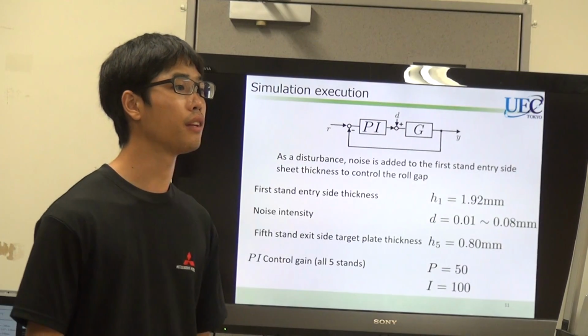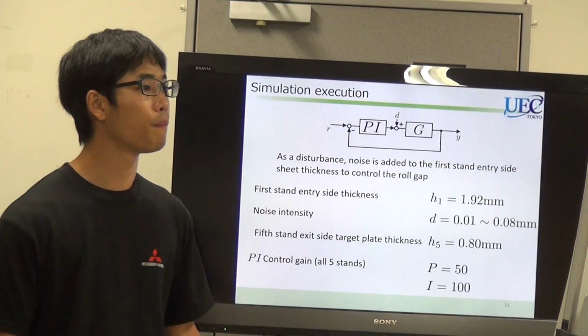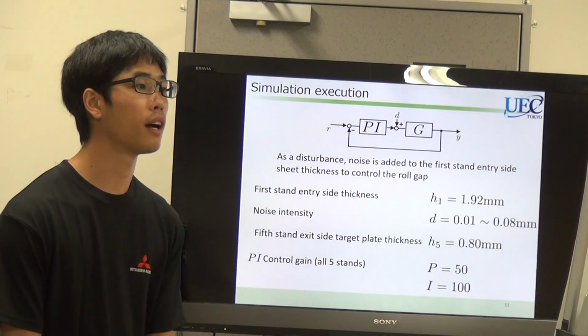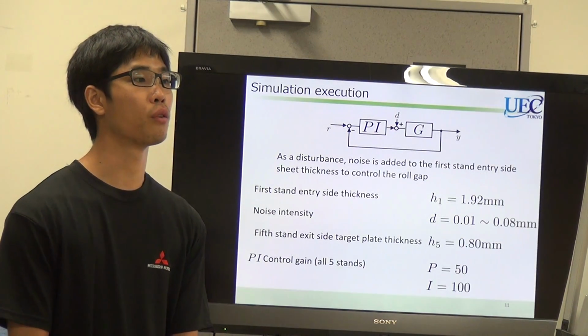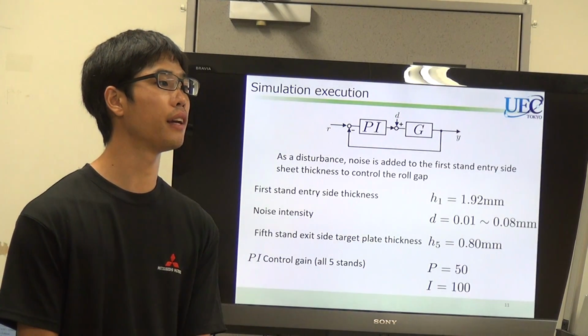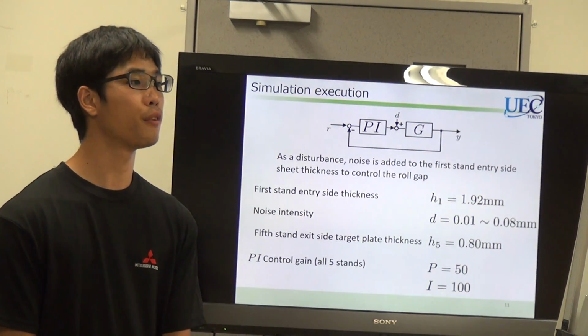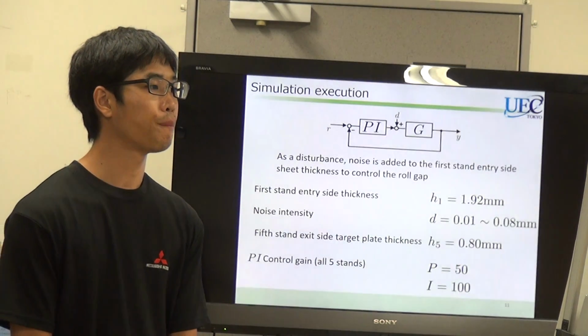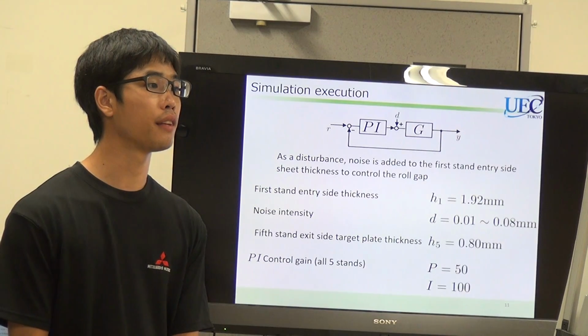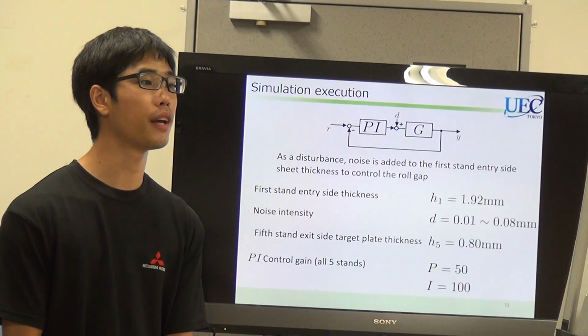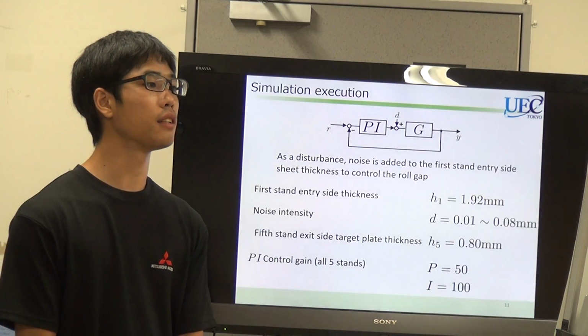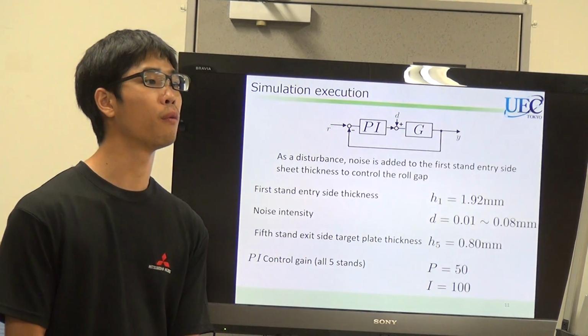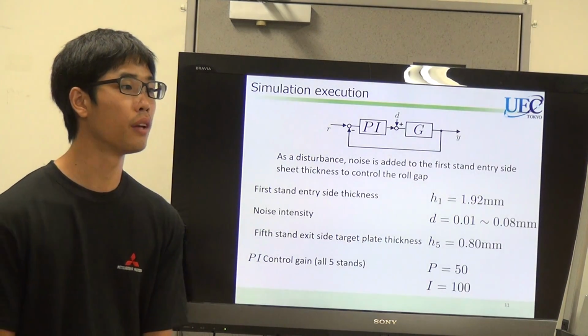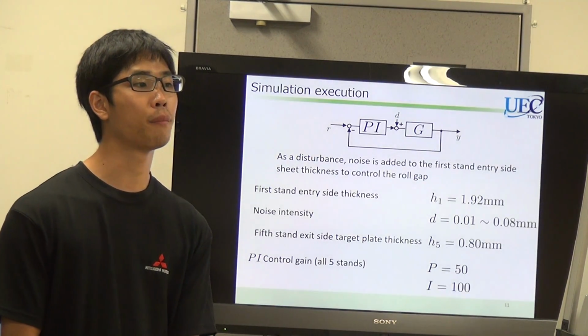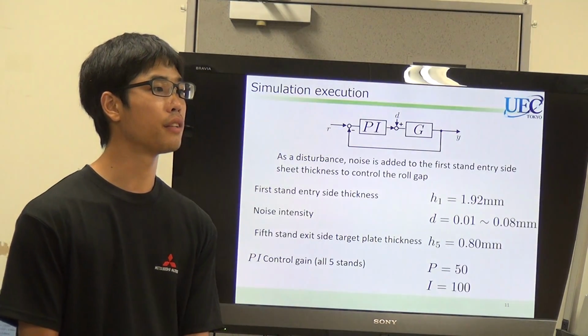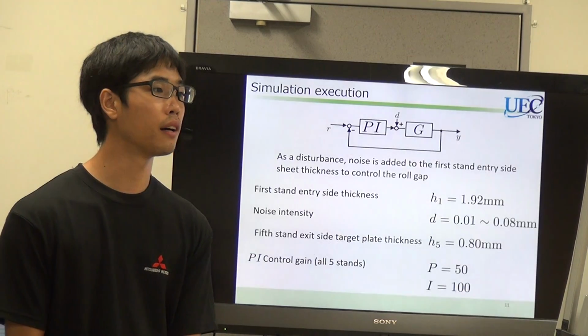Here, simulation using a simulator was performed simply. We set PI control against roll gap and set up a comparison of the change of plate thickness due to disturbance with a simulator without roll control. For the first stand entrance plate thickness, noise with weights of 0.01 to 0.08 millimeter is added as disturbance with respect to 1.92 millimeter while changing it every 0.1 seconds.